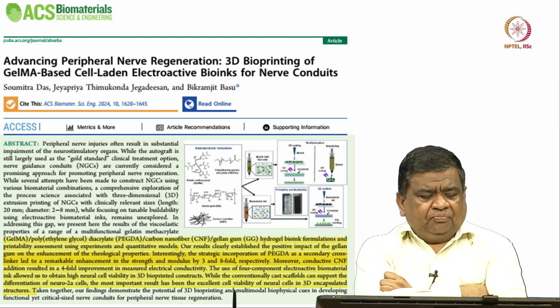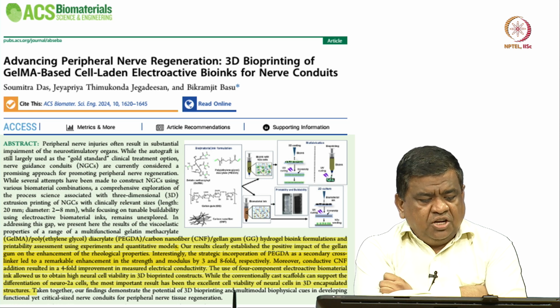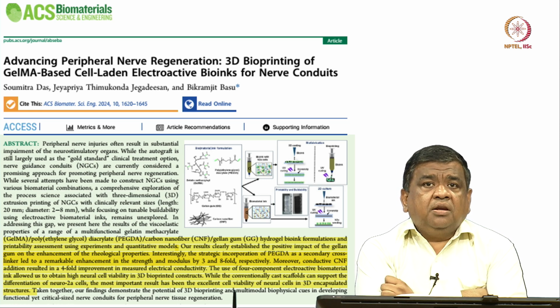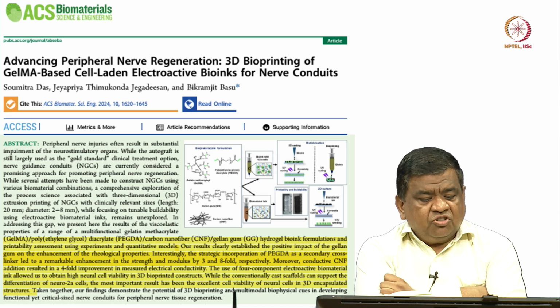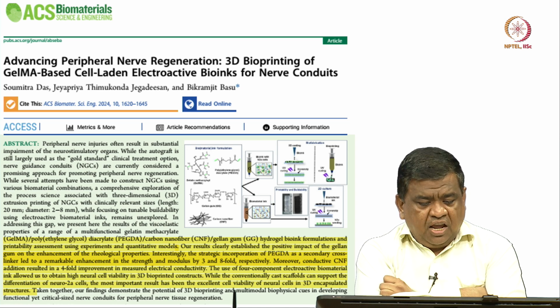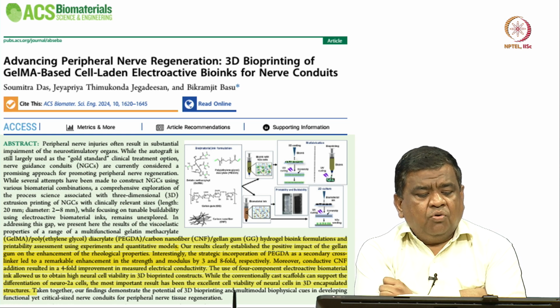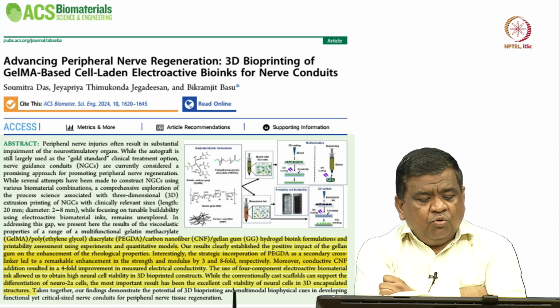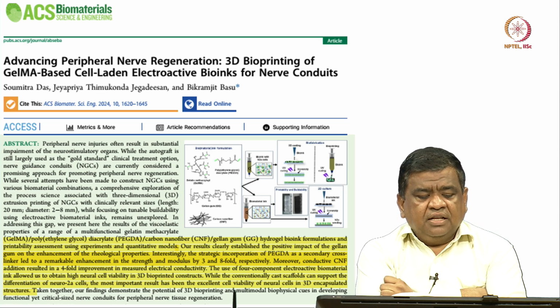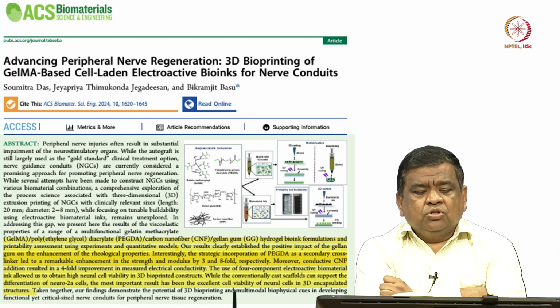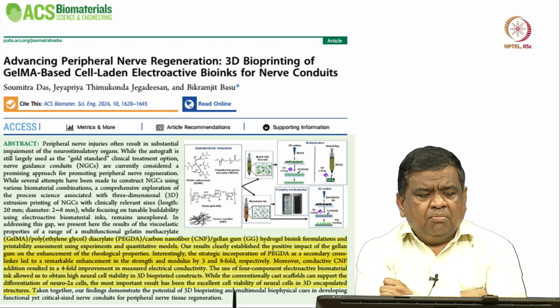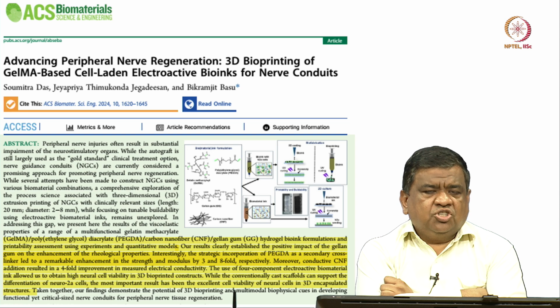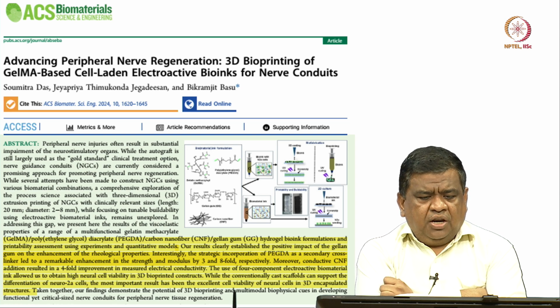One of the major conclusions was that the conductive carbon nanofiber addition resulted in a 4-fold improvement in electrical conductivity, and strength and modulus were enhanced by 3 and 8-fold. These scaffolds can support the differentiation of Neuro 2A cells, and the most important result has been excellent viability of neural cells in 3D encapsulated structures. This work was recently published in 2024, and you can see more details in the published study if you are interested.